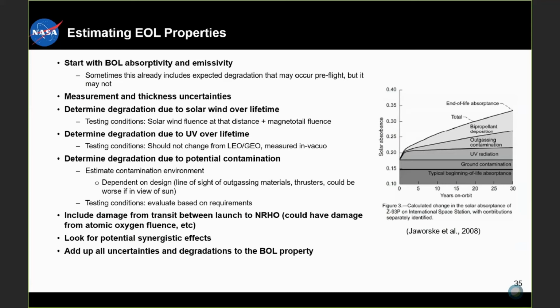So some other important things to think about is that it's not just the degradation that you'll see in the environment that you're targeting, it's also going to be the degradation that you'll experience in transit to that environment. So one thing for NRHO is that even though we don't have atomic oxygen in NRHO, we will have atomic oxygen on the way to NRHO. So we'll need to assess, will the time that we're in low Earth orbit be long enough to see atomic oxygen damage? And then if we think it will be, then you'll have to do some testing to determine what degradation effects we're going to see from that.